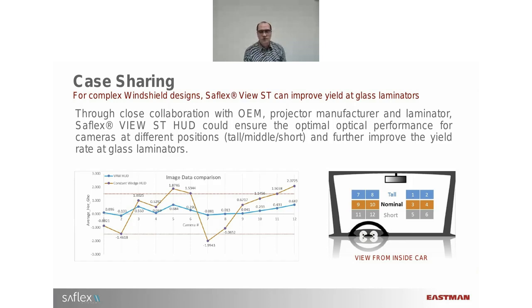If you look at the short and the tall driver, you will see that if you would use the same tolerances, sometimes you pop out. So it means that if you're a short driver or a tall driver, your image will not be as nice as for the nominal driver. So by adapting and introducing the ViewST, you see the blue line on the same type of windshield, and you see for all the drivers, they obtain a very good image.